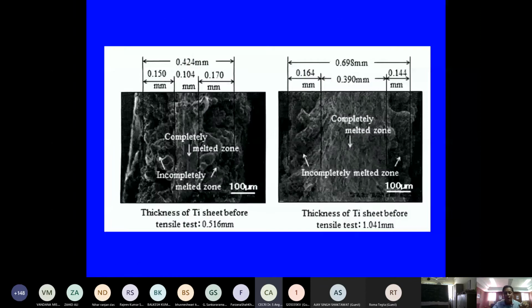Basically, the process parameter we need to keep in mind, as I mentioned, is that when the laser beam is scanning the powder, it makes a completely melted layer, and surrounding it there will be a lot of incompletely melted particles or powders attracted toward the melt pool zone. You can see in this slide, although I have clearly marked the layer thickness that I am printing, so much powder is getting attracted towards this. So we need to either remove those powders, or develop a technology so that the unmelted powder gets melted and fused to the surface.